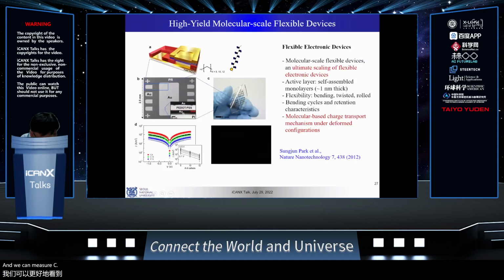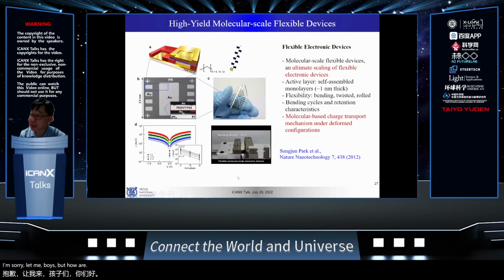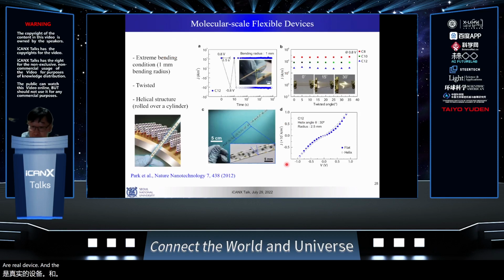I'm sorry about a little bit of noise, but this is how we measure it. We can do the flexible measurement. We repeat this cycling, the bending cycle, and then we measure. These are images of the real device, and the junction yield is great, very stable. High current is the short length, middle current is the middle length, and low current is the long length.